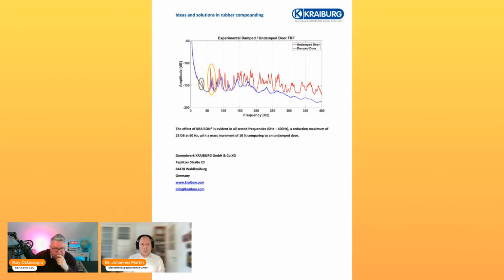And this is not only a very nice advantage of the Kraibon material, it also reduces vibrations. So not only a structure-borne sound dampening effect, but also the vibration of the full part. That means as soon as you have neighboring parts of this carbon part, it leads to less stress on this neighboring part. And also if you have a connection of the composite part with a metal part or with other parts you find in a car, there's less stress in the joint of this material.